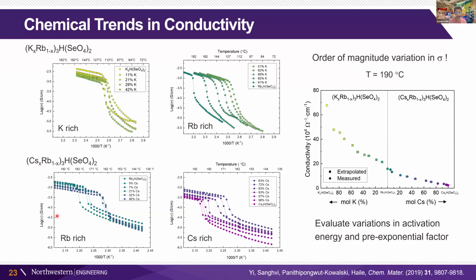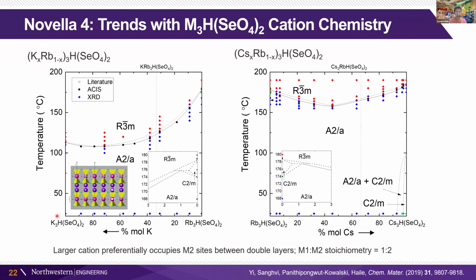Which is the solid solution system between the potassium rubidium and the cesium rubidium. And what we see here is that they make full solid solution just below the transition and full solid solution just above the transition. And I apologize that my pointer is not going to work because of the lag. But what you can see is that there is a general trend towards an increase in the transition temperature as we increase the size of the cation. So you see that fairly clearly on the potassium to rubidium side.